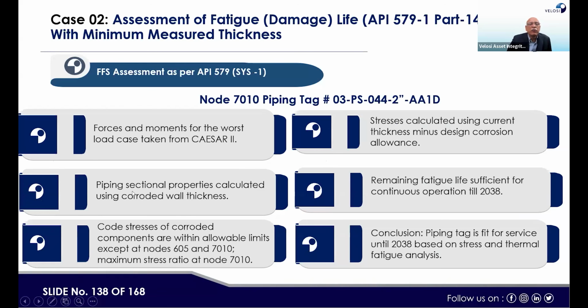So what we checked here: forces and moments for the worst load case taken from Caesar II, and piping sectional properties calculated using corroded wall thickness. Code stresses of the corroded component are within allowable limit except at nodes 605 and 7010. Maximum stress ratio at node 7010 observed. Stresses calculated using current thickness minus design corrosion allowance. Remaining fatigue life sufficient for continued operation till 2038. Conclusion: piping tag is fit for service until 2038, based on stress and thermal fatigue analysis. This is the result basically.